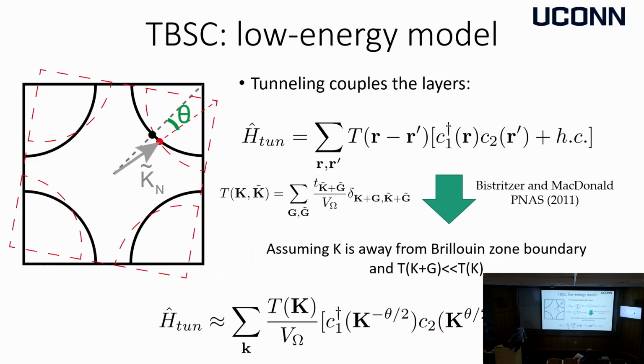The difference in twisted nodal superconductors is that those Dirac points are not fixed to be at any high symmetry point of the Brillouin zone. They have to be along a high symmetry line, but they can be pretty close to the origin, which allows you to neglect all these higher order processes and just limit yourself to one tunneling process which couples those two displaced Dirac cones. That's that.